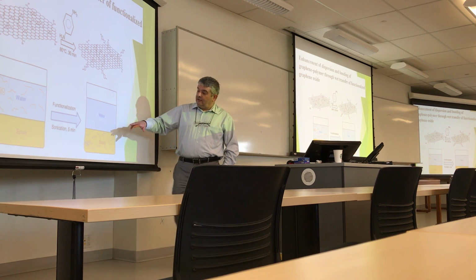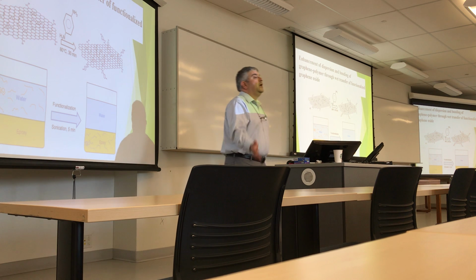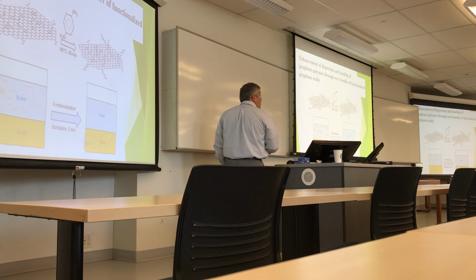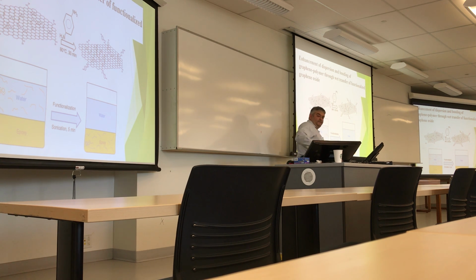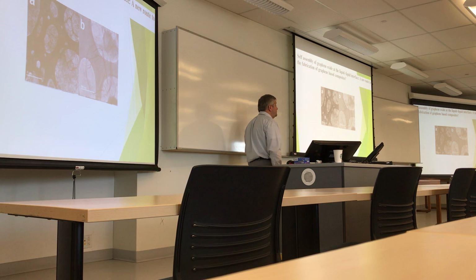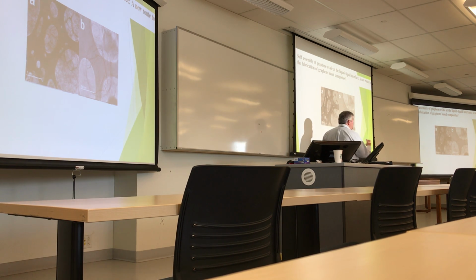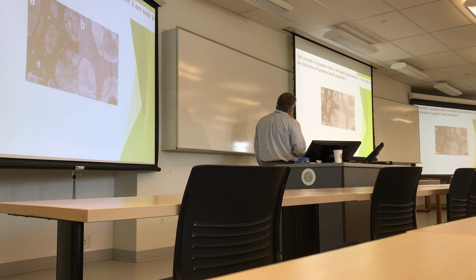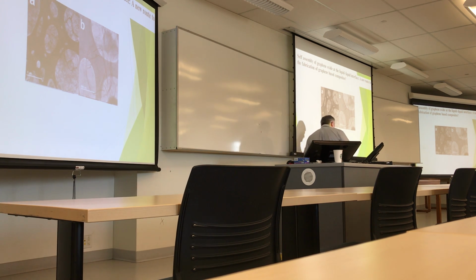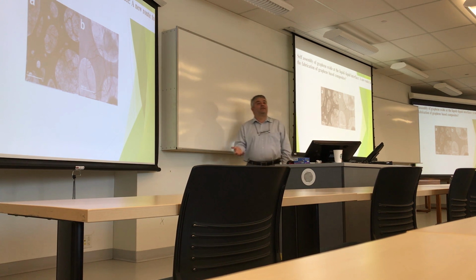So what happened was that functionalized GO went to the epoxy phase, and we decanted the water, and we had epoxy, and we got the properties from it. So we kind of improved the bonding between the polymer and the GO using the functional groups. One thing we found out as we were playing with GO was that GO is more hydrophilic than graphene, but it's not totally hydrophilic, it's actually amphiphilic. And that provided a great opportunity because it could work as a surface active agent.